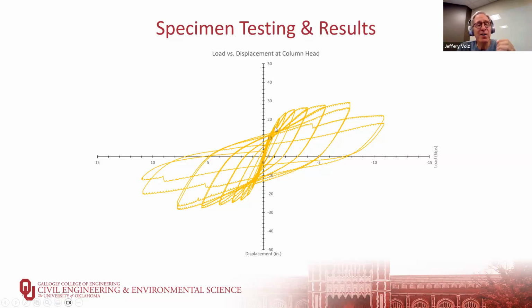The other thing is you have a cold joint between the concrete and the column base, which is typical of construction. You're going to have a cold joint there, which is okay because we don't count on the tension capacity of concrete in our capacities. So whether it's a crack that forms or it's a cold joint, that's what the reinforcing is for. But the concrete starts to become nonlinear once you start exceeding about 40% of the ultimate compressive strength, and the steel bars start to become nonlinear. So eventually you start yielding the bars.